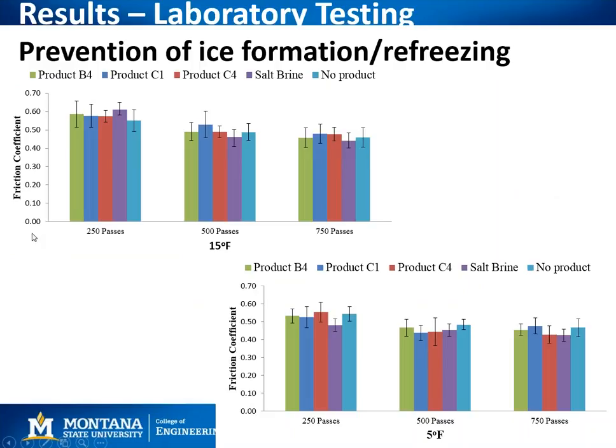So what we have here is two figures, and we have friction coefficient on the y-axis and the number of passes on the x-axis and the different product types. And what you can see here is that at 250 passes, you have a pretty high friction coefficient that steadily decreases with time. So the roads are getting more and more slippery with time at 15 degrees. And there's a similar trend, but a less pronounced trend at 5 degrees. Basically, the roads are just slightly more slippery at 5 degrees in general.